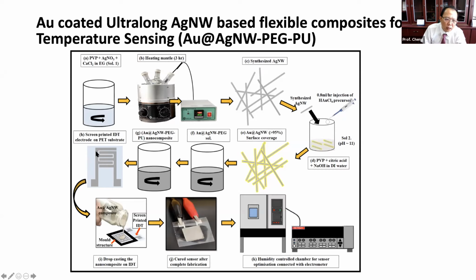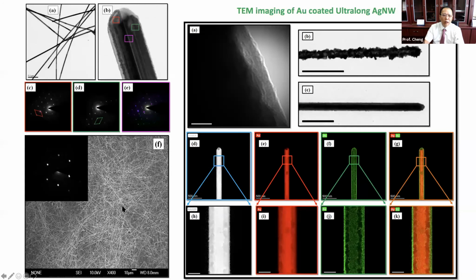Then we spin coat on the IDT electrode, and the final sensor will look like this. So we put it into the oven, and we can test the electrical signal. So this is what we've done for the temperature sensing. Then you can see this is the silver nanowire synthesized in our lab. All single crystal, and the aspect ratio is about 1,000. And each silver nanowire is 100 nanometers. So you can see this is an element mapping. This is the silver, and the green part is gold. So you can see the gold fully covers the silver nanowire.